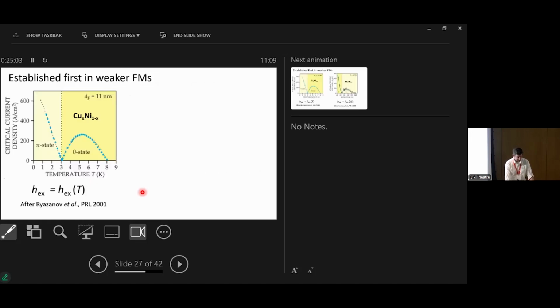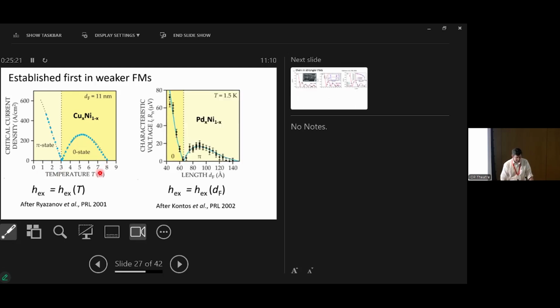So this was established firstly in Chernogolovka about 20 years ago. They used a weak ferromagnetic alloy, copper nickel. And here they saw, this is in a Josephson junction, the critical current is non-monotonic in temperature. And then later in France, they showed a similar thing with another weak ferromagnet, but now they could study this as a function of thickness.